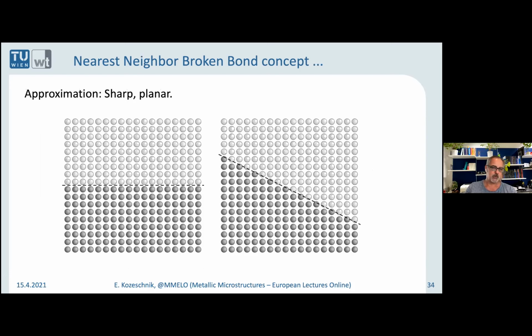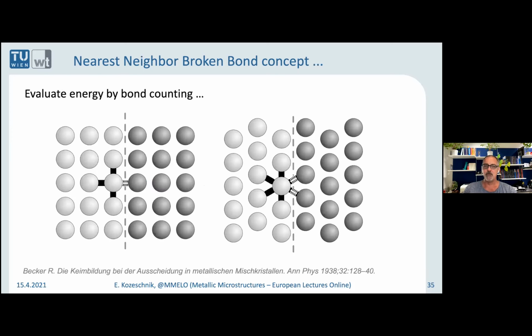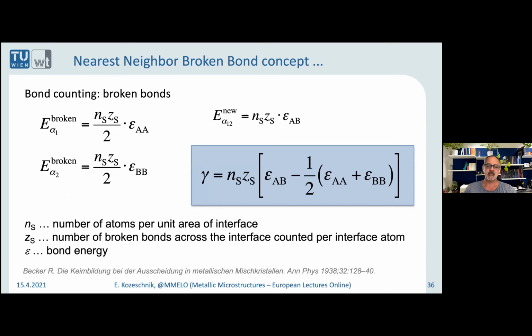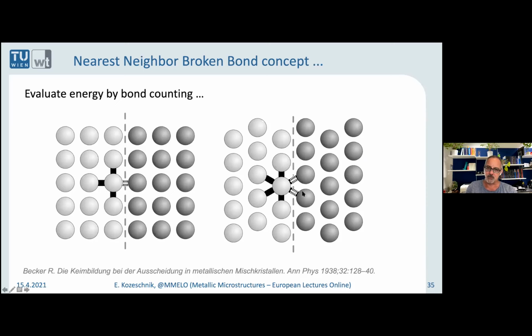What Becker assumed was, let's take a sharp interface. These are two sketches of sharp interfaces. That means the two phases are exactly separated by a planar and sharp interface. No atom is on the wrong position. No entropy. That makes things a little bit easier, because when we can ignore entropy, we just have to count the bonds. The suggestion was, let's count the bonds across the interface, and let's separate them, and evaluate the broken bonds by this thought experiment. This has been done by Becker already in the nearest neighbor approach. That means only the bonds going to the nearest neighbors are counted, the rest is ignored.